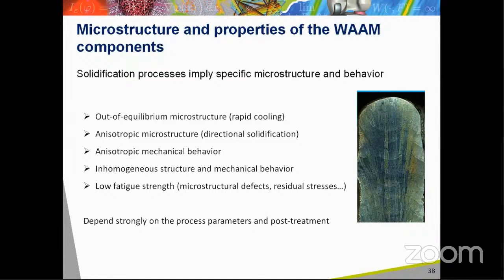an anisotropic microstructure due to a directional solidification phenomenon, a corresponding anisotropic mechanical behavior, inhomogeneous structures and mechanical behavior, and a low fatigue strength, mainly due to the microstructural defects and to the residual stresses formed during the process. All these factors depend strongly on the process parameters and post-treatment.